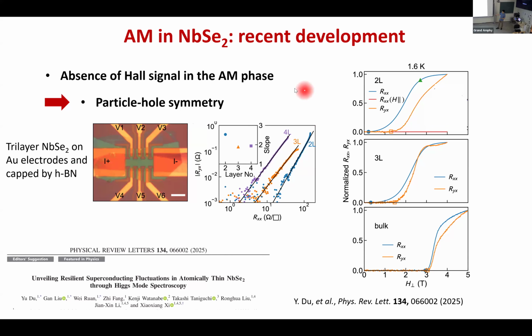Then this is also seen here in their sample for either a bilayer or a trilayer. You see that the blue curve shows you finite resistance when you apply some field, and then the orange curve shows that they don't see Hall resistance up to this point. So within this range is the anomalous metal phase, but you don't have the Hall coefficient. You don't see Hall effect. So it's like particle-hole symmetric.